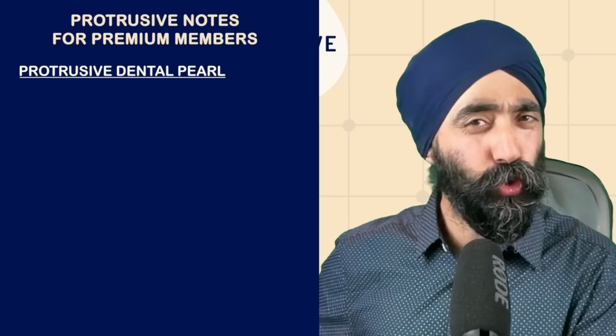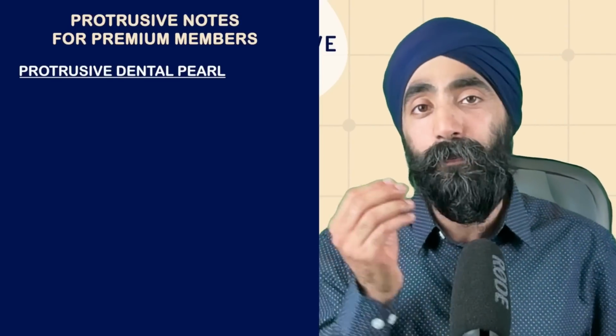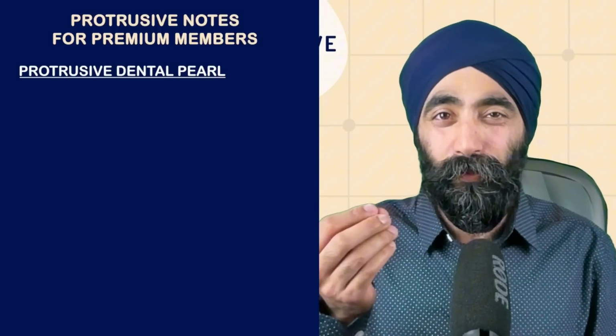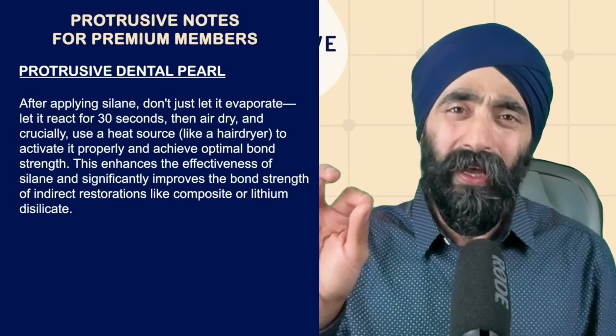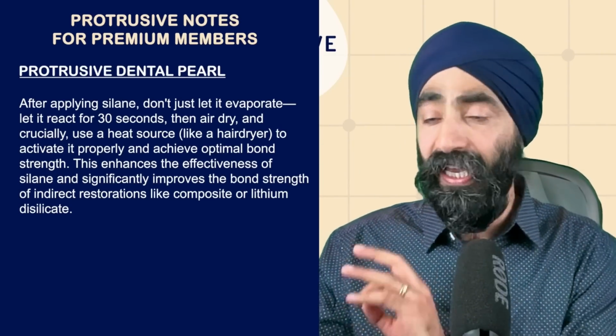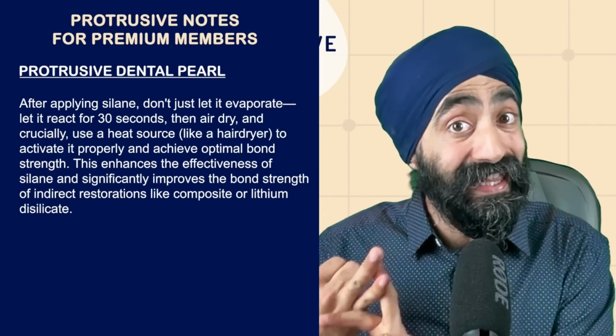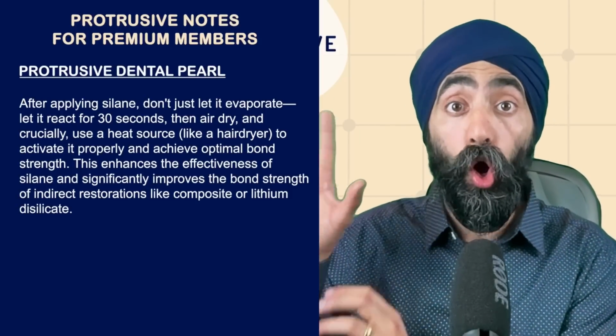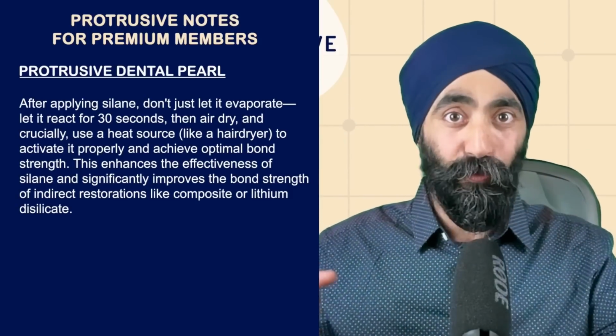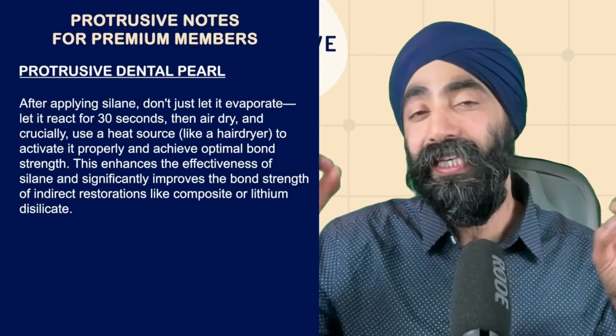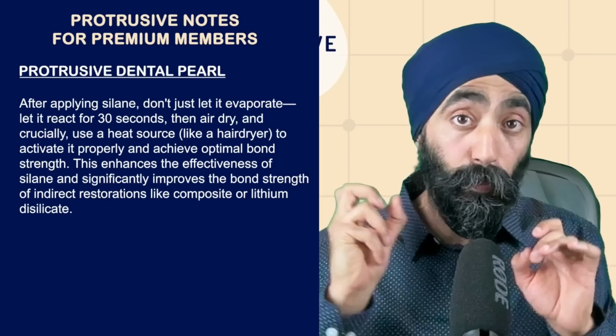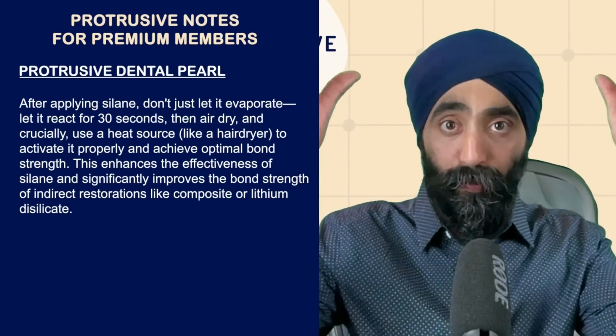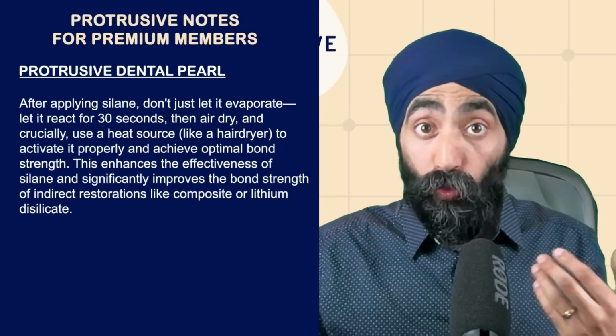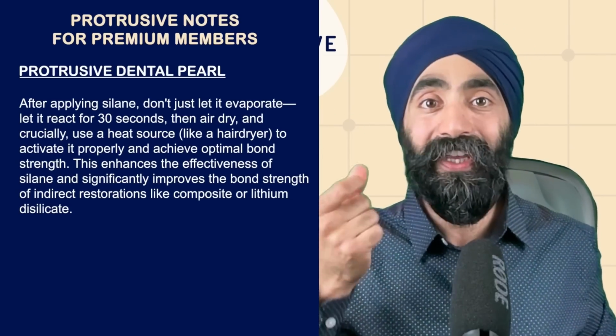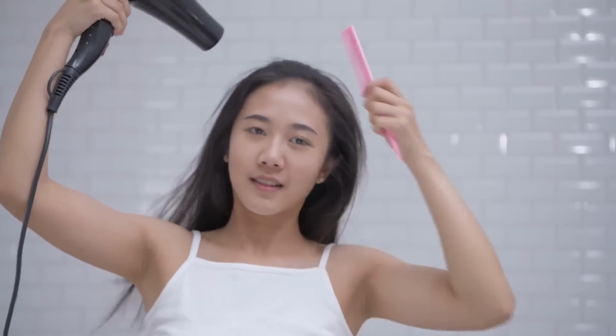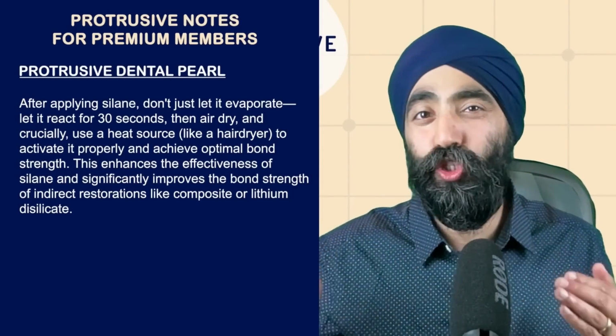Every PDP episode, I give you a Protrusive Dental Pearl, and today's one is, of course, inspired by Pascal Magne and an adhesive protocol tip. The tip is when it comes to the silane step, that step is so critical in whether you're bonding an indirect composite or an indirect ceramic such as lithium disilicate. Once you've done the correct surface preparation of your indirect restoration, so that's different for composite, which you'll hear at the end, and that's different for ceramic, and once you get into the silane stage, here's what you don't do. You don't just apply silane and leave it on the side to let it evaporate. No, you want to let it react for 30 seconds, then you want to air dry it, but then you want to use something like a hairdryer. You need to use some hot air to achieve the perfect layer and the perfect chemistry of your silane.